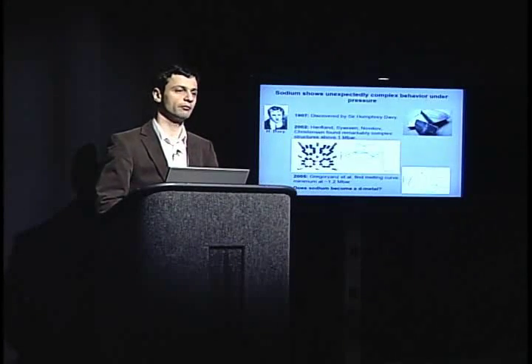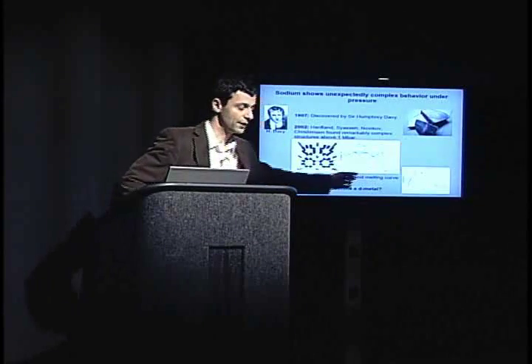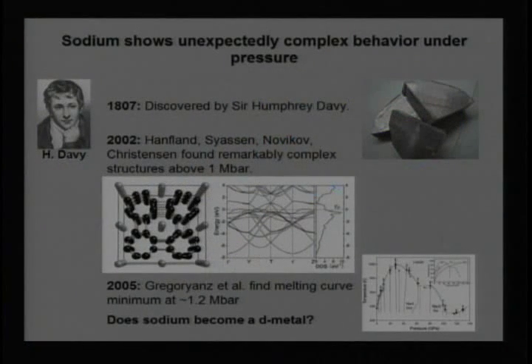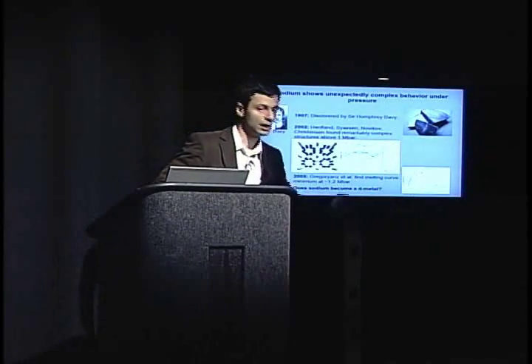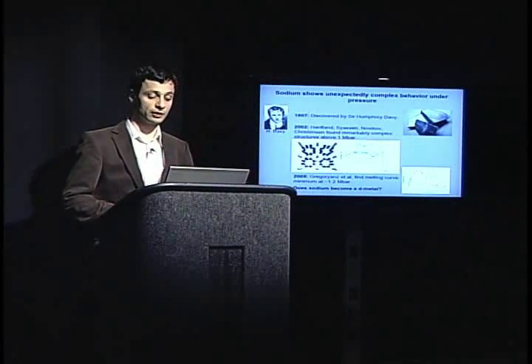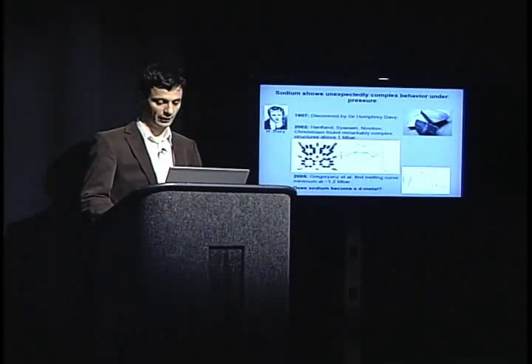A few years later, British scientists found that sodium exhibits a very unusual melting curve. As you can see, at first the melting temperature increases with pressure, and then it begins to bend down, and at pressures of about 1 million atmospheres, slightly more than 1 million atmospheres, exactly where structures like this are formed, it has a deep minimum, and sodium melts actually at room temperature. So usually, as you compress materials, the melting temperatures increase. For sodium, the behavior is much more complex. And at very high pressures, it actually can melt at room temperature.